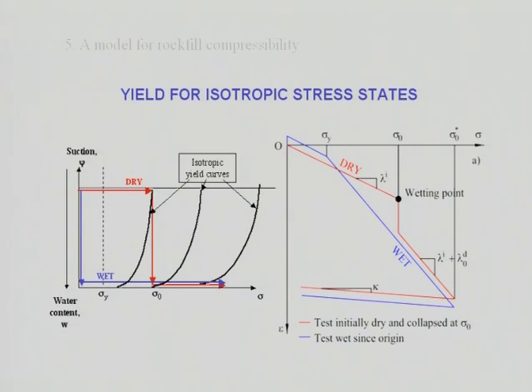Here you have theoretical behavior of a dry sample. You load it, at some particular point you wet it, and you have a collapse, and then you continue your loading under saturated conditions, you unload it, etc. And if you have a sample initially dry, and then you wet it initially, and then you get some expansion here, and then if you load it, this is essentially elastic because our stress is smaller than this threshold value, but here you begin to yield, and then here you have your normally consolidated line for saturated conditions. Now, this is an explanation of what you measure actually in the oedometer.